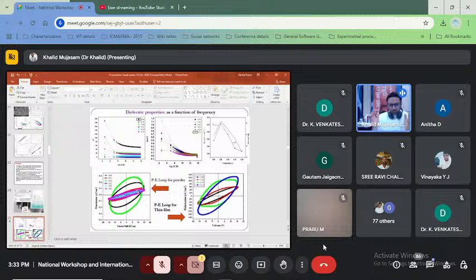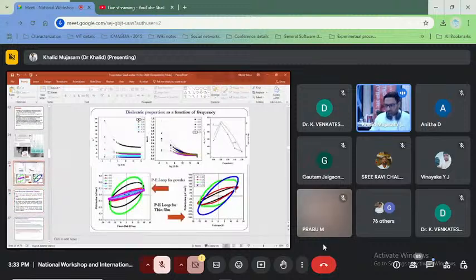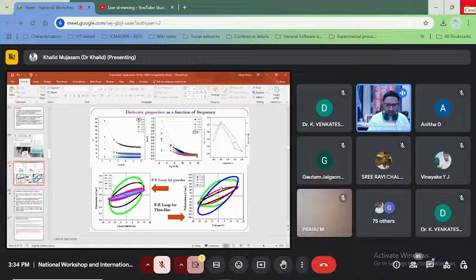So what we did, we used the same powder material. We thought, okay, let's not waste this material, and we pressed it into a pellet and used it as a target material. With the help of the E-beam, we developed a thin film. After developing the thin film, we got a better loop enhancement. So the loop has increased, and it has gone from 0.3 to a very wide loop, to 140 microcoulomb per centimeter square remnant polarization, achieved for a voltage of almost 15. So that was a kind of remarkable thing.